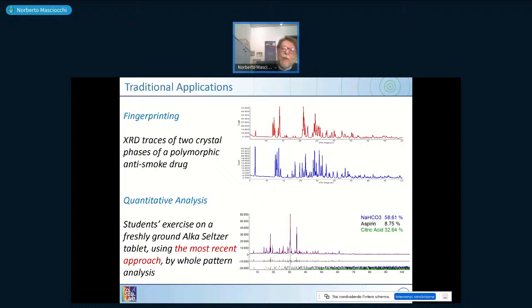Then you can also think, once you have recognized what is in your material, can we detect how much of this material is present? For example, what you see down here is an example I normally do with students in a third-year course. I take a commercial drug which is called in Italy Alka-Seltzer and is used as an antacid in the stomach when you have eaten too much. If you run the spectrum, you see different peaks. It is known that Alka-Seltzer contains aspirin and citric acid. I can also see that the major part is hydrogen carbonate. So this antacid is not only citric acid. It only gives you a nice flavor.